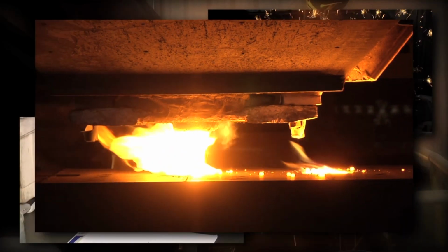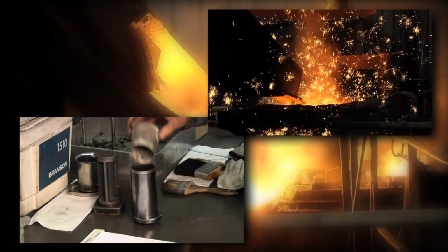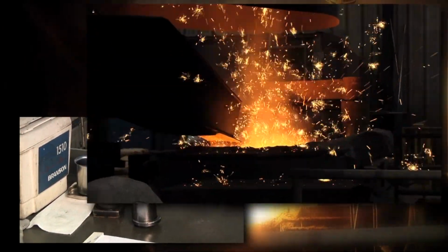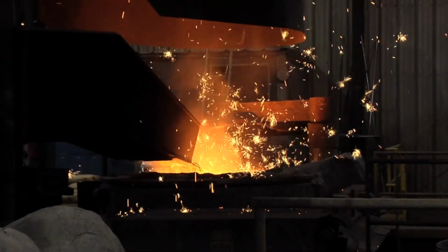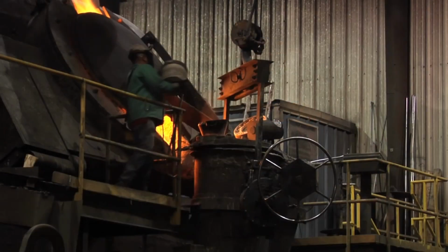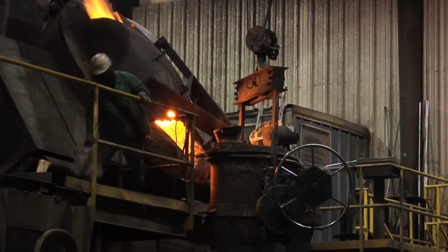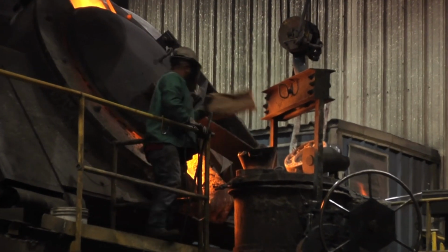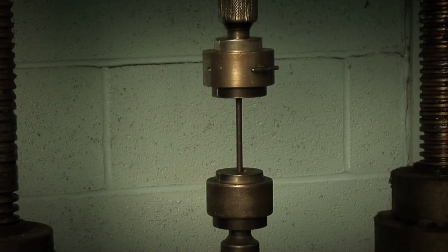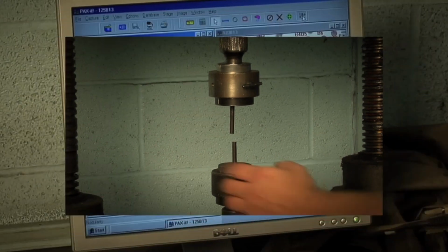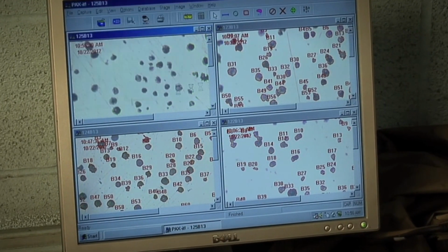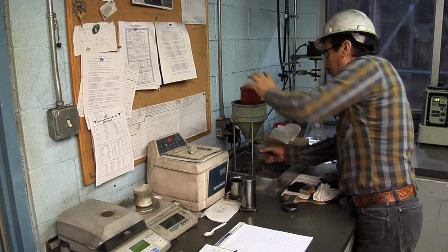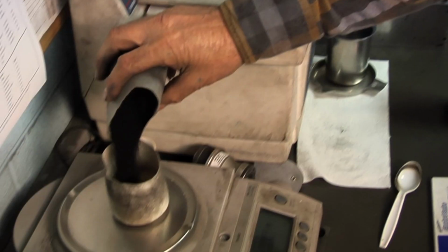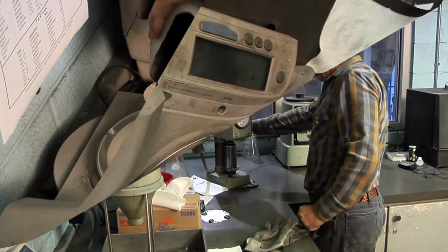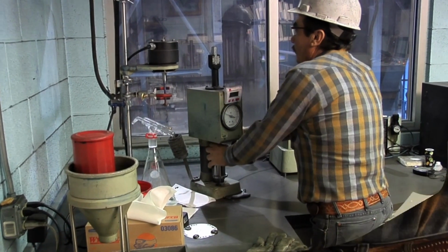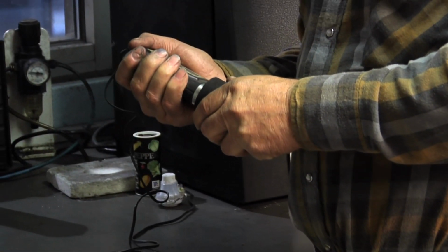into a mold. To begin the process, two quite different steps take place simultaneously. Recycled metals are introduced into two 15-ton melting furnaces, along with certain precisely measured alloys that combine to create our high-quality ductile iron. Base iron samples are taken and allowed to solidify, and then run through a rigorous quality assurance system to verify the iron's properties. At the same time, mold sand preparation is achieved by the proper mixture of sand, water, carbon, and clay, and then run through its own vital quality assurance testing.